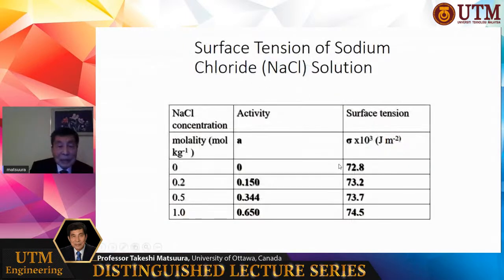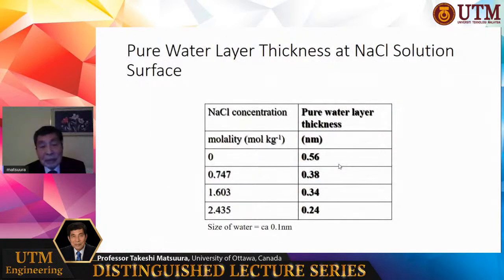And this equation tells that on the surface of seawater or salty water, a very thin layer is formed, and the thickness of the pure water layer on top of the salty water is like 0.56 nanometer down to 0.24 nanometer, depending on the concentration. This is for sodium chloride solution. 1 nanometer means it is 10 to minus 9 meter. And this fraction of nanometer corresponds to a few water molecules. The size is a few water molecules.